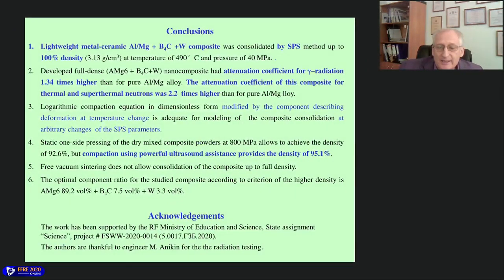articles, journals. As a conclusion, I can say that the lightweight metal ceramic aluminum magnesium matrix nanocomposite also consisted of inclusions of boron carbide powder and tungsten nanopowder. This composite was consolidated by the spark plasma sintering technique up to full density, up to 100% of density. And the absolute density of such material was 3.1 gram per cubic centimeter. And the optimal modes of the spark plasma sintering were found, such as temperature and pressure during SPS.